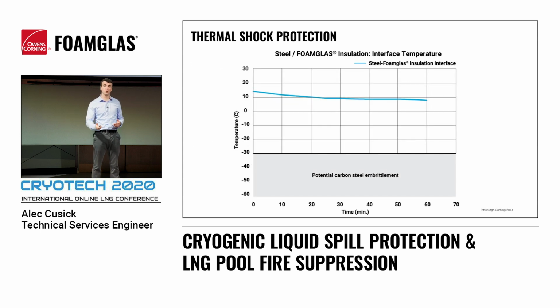Here you can see the results of that interface temperature between the foam glass and the steel plate. On the bottom, you can see the temperature range where you start to get worried about potential carbon steel embrittlement. And you can notice that over the course of a 60-minute test, we were able to maintain an interface temperature well above where you start to get concerned over that temperature range, never dropping below around 8 degrees Celsius.